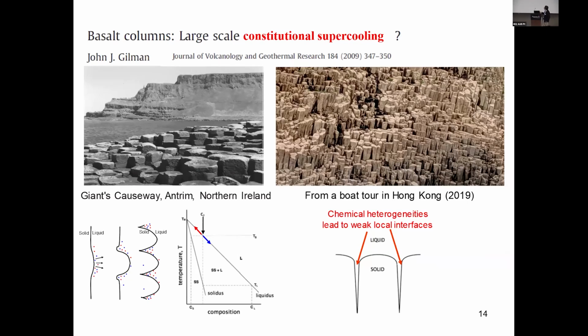So in this phase diagram, as we cool, lowering the temperature of the liquid melt of the alloys, when we touch this liquidus line, the purer phase will have a higher freezing temperature, while the more impure phase would have a lower freezing temperature. As a result, at a solid-liquid interface, these impure atoms will be pushed away so that locally we can have this initial freezing. That causes this morphological instability, producing this columnar cell structure.